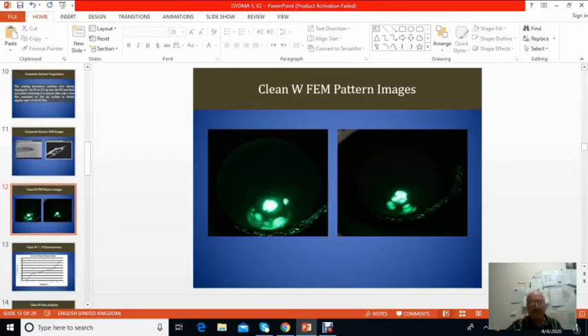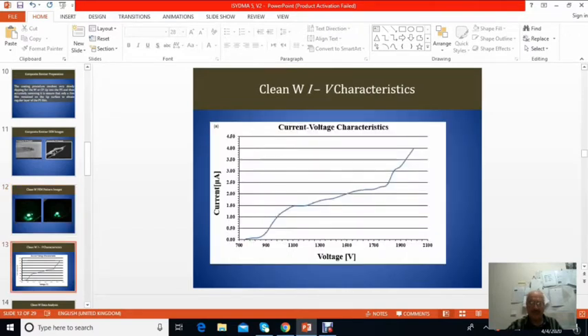Clean tungsten field emission microscope pattern images. This is the image from clean tungsten. You can see some sort of 4 spots. If the tip was very clean, then you see the 4 spots more clearly. 1, 2, 3, and the 4th more clearly. But this is not a very clean tip, by which I mean that the student who did the work did not clean the tip ultrasonically well after the etching process. So this is the current voltage characteristics. This is the IV characteristics, the standard of the tip. You can see this is different from what we have shown before because of the not very clean tip.